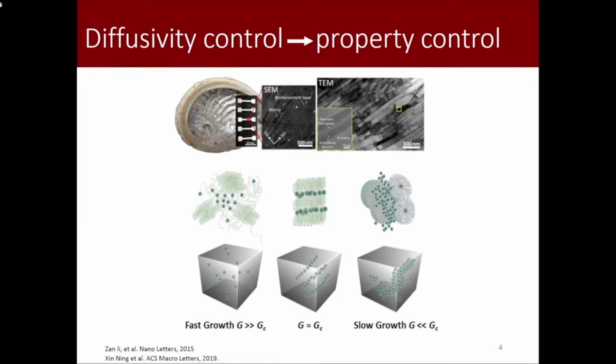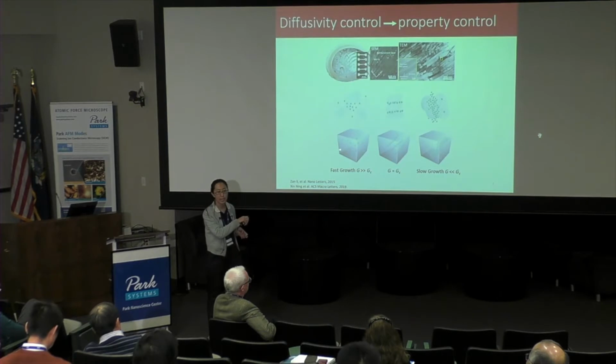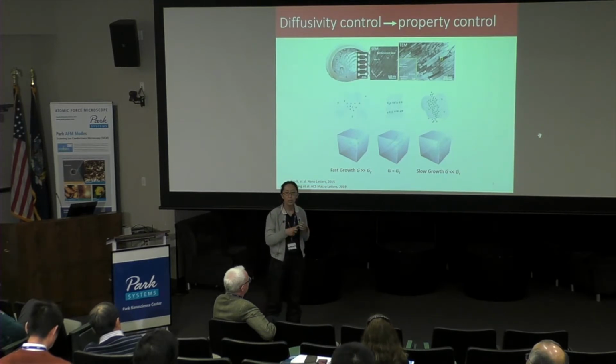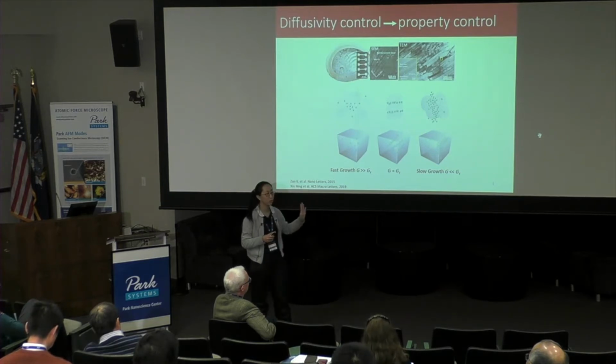After doing the surface modification of nanoparticles, the surface energy is tuned, and nanoparticles can disperse well in the polymer matrix. If we quench from the melt state to room temperature, the nanoparticles will not have enough time to move around because the crystallization rate is very fast, and they will be engulfed in the polymer matrix and stay where they are. However, if we slow the crystallization rate, the nanoparticles will be pushed into the solidification front in order to release the thermal energy.